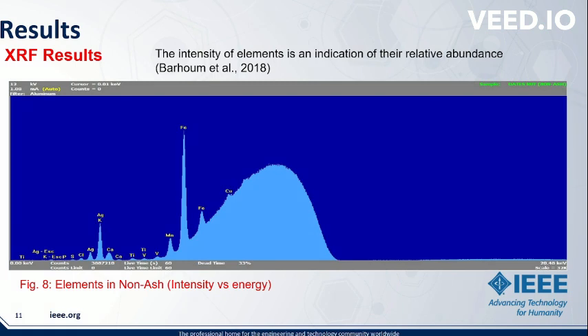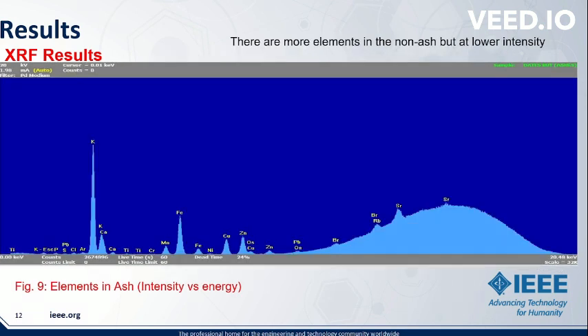In the qualitative XRF analysis, the spectra show the minerals present in the date palm seed sample. For the non-ash, we could see iron, silver, potassium, copper, manganese, all having spikes. The intensity of the elements are an indication of their relative abundance according to Barhoum et al., 2018. In the ash sample, there are more elements, but these elements are at lower intensity. Of course, potassium was still the most predominant, followed by iron, and then calcium, then zinc.